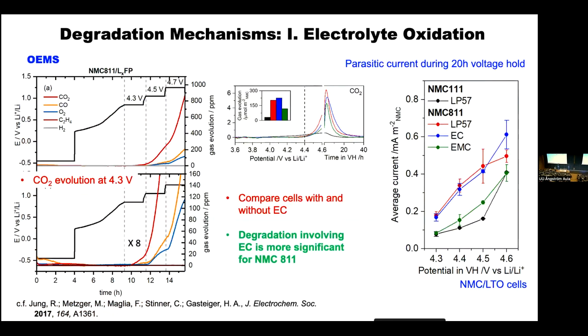So then what Wes did was to pull the whole thing apart and say, let's look at the degradation in EC cells, let's look at the degradation in EMC cells, so cyclic versus linear cells, and compare them with this full electrolyte, the LP57. He was able to show that you've got significantly more degradation in the cells containing EC. The degradation was seen by signatures such as the carbon dioxide evolution, which is the signature of EC degradation. It was also seen by things like a parasitic current, where you hold the cell at high voltages or increasingly high voltages, and you look at the parasitic degradation current.